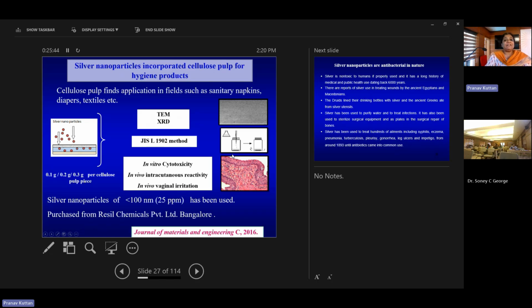So initially we developed silver nanoparticles and incorporated them in cellulose pulp, and we checked different tests. But later it was found that we need this amount in large quantities, so we didn't make it anymore. We purchased the silver nanoparticles from a company called Resil Chemicals. They can provide us in large quantities. We obtained silver nanoparticles of size less than 100 nanometer, and we incorporated them in different quantities, 0.1, 0.2, 0.3 per cellulose pulp piece. And we did different studies to see the optimum concentration which will give antibacterial property without any toxicity.